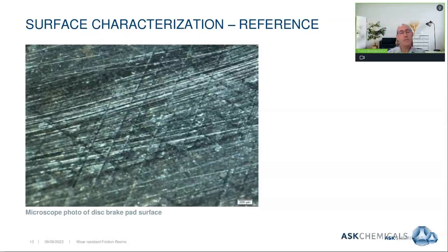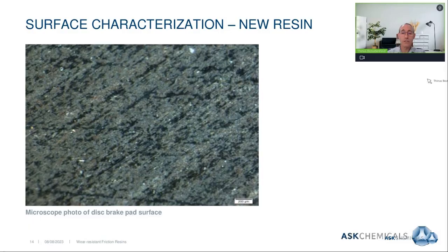And immediately you can see a substantial wear behavior in the form of plowing effect. You can see the plowing effect across the surface, and you can see the worn away binder matrix, or the matrix in total. We then move across to the new technology, a micrograph of the new technology.